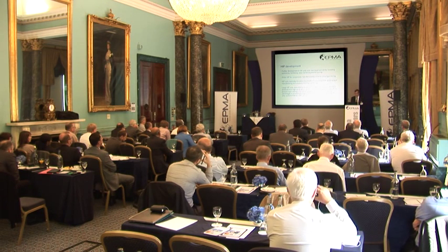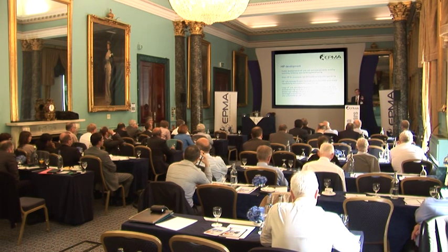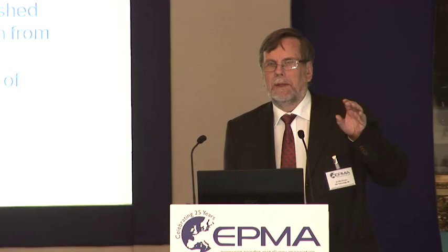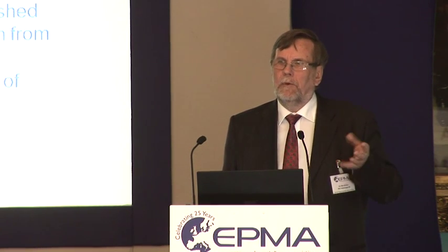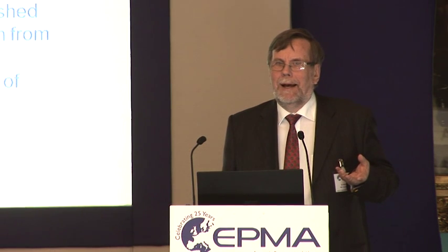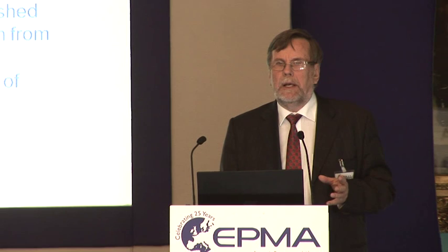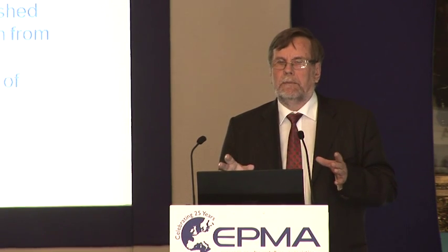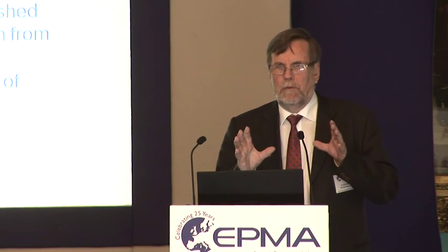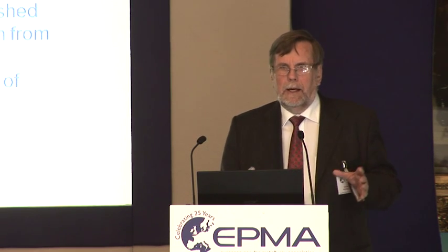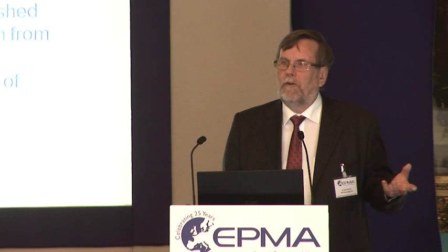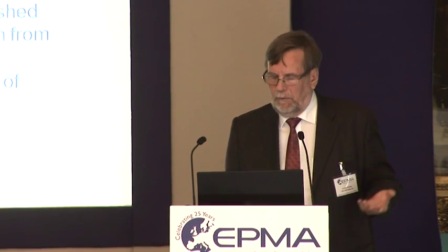Further development of the equipment itself with heat treatment ability, quenching, hardening, case hardening, and tempering. What I was thinking about when I brought this up is that for conventional sintered steels, you have a density now with high pressing which is quite close to getting closed porosity. If you increase the temperature somewhat and have high pressure, you will come to a situation with closed porosity, and then you can get manufactured parts with full density. You will need some grinding, of course, to fix the tolerances. But I could see that a sinter HIP for steel products will be coming.